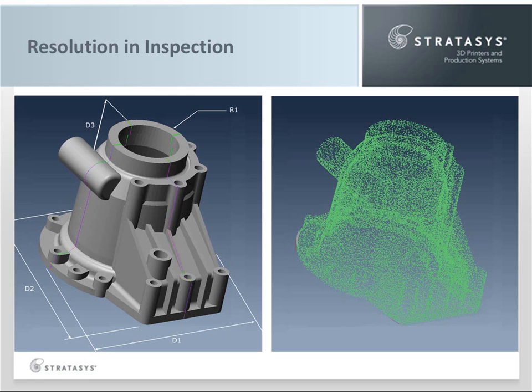A similar myth exists in the inspection or the quality arena. Think back on our 12-inch ruler example. Expand that to a three-dimensional measurement system. One method or tool measures a small number of points, but measures down to, say, 1/10,000th of an inch. While another method may have hundreds or even millions of measurement points, but may only measure to 2/1000th of an inch. In this case, some want to believe that more points mean more accurate measurements. It's not necessarily true. The accuracy of the measurement device is a result of the device's capabilities, not the number of points it measures. Choose a measurement tool or technique that has an appropriate resolution for your application requirements. In the remainder of this study, we'll use a highly accurate 3D laser scanner to compare different parts.